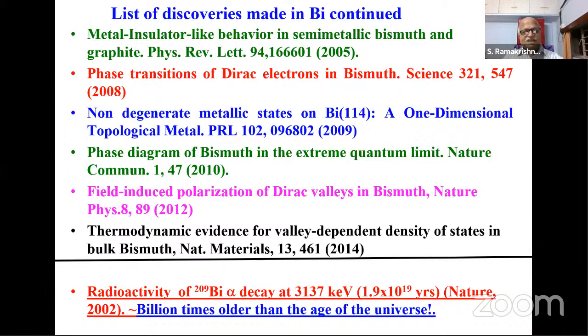The most interesting thing about bismuth came from our high energy colleagues. They found that bismuth, which was used for medicine, for treating stomach disorder and so on, shows alpha radioactivity, which is at 3.1 MeV. And a good thing about alpha activity is that it dies before it comes out of the bismuth atom. It's such a short range. But then the half-life is about 10 to the power of 19 years, which came as a Nature paper some 18 years ago. So this is a billion times the age of the universe.